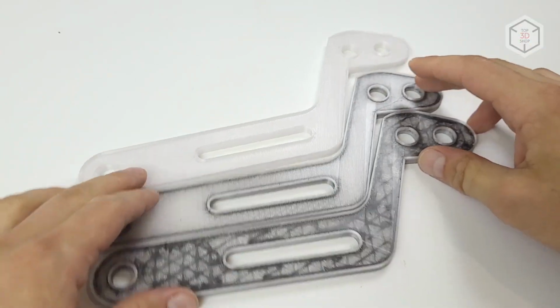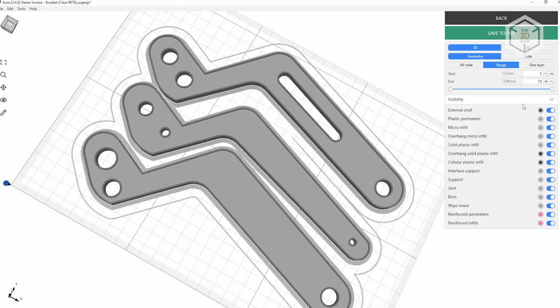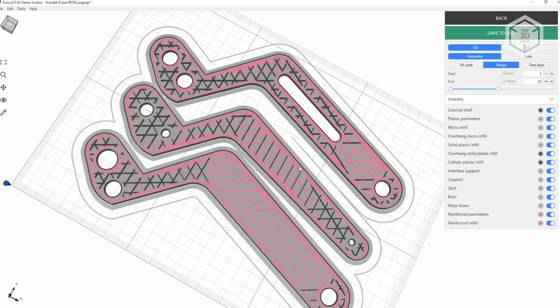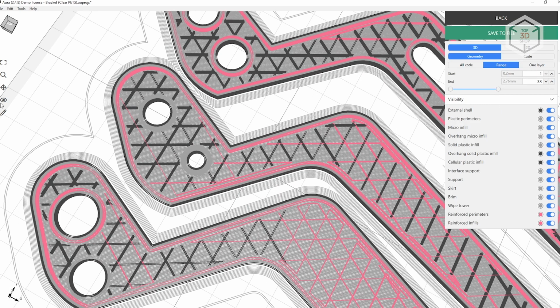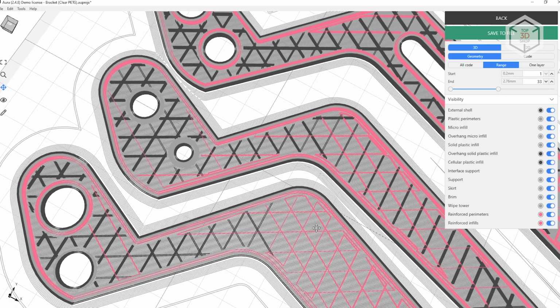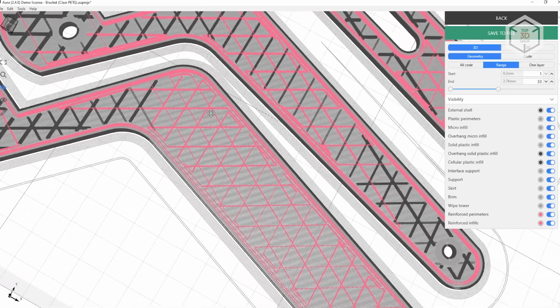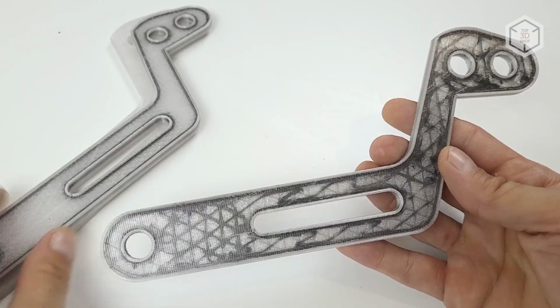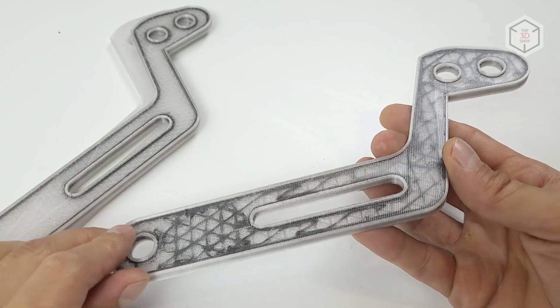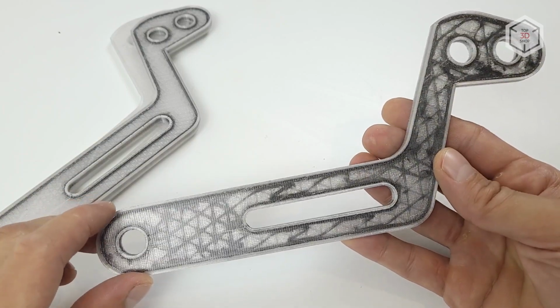In addition, at the modeling stage, we encountered constraints related to the minimum distance of fiber printing. For this reason, the holes in the part are as small as possible for Aura to design reinforced contours around them. And in the narrow areas near the notch, the reinforced infill turned out to be incomplete. In the most important areas, though, everything was printed as it should be, but this had to be taken into account when modeling.